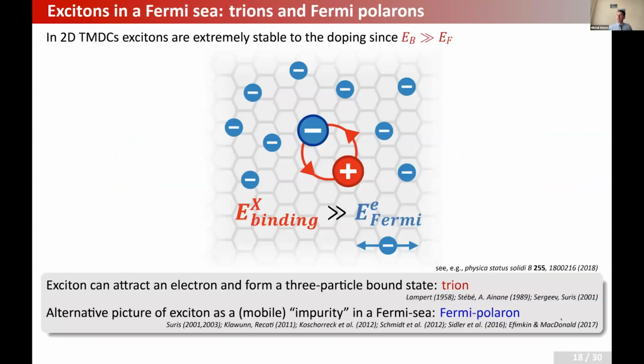The first thing is that because of the very high binding energies of excitons, hundreds of milli-electron volts, for any reasonable doping, with Fermi energies on the order of several milli-electron volts, maybe 10 or 20 milli-electron volts, the exciton binding energy is huge and the Fermi energy is small. That is why typically excitons should be very stable. There is no screening of the Coulomb interaction in that case. The screening should be dynamical, and dynamical screening is not efficient. However, what can happen is that this exciton can pick up one of the resident carriers and form a bound state, which is called a trion.